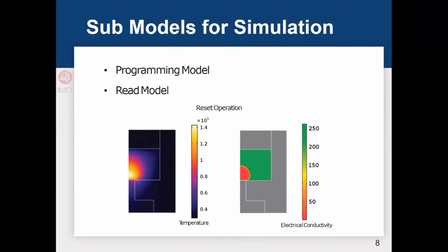So in the reset operation, we will have to increase the temperature so much that it actually crosses the melting temperature of GST, so it goes into the amorphous state, and the resistance is actually so high. And in this picture, we can see there is a white, small line that's showing the temperature over the melting temperature, 873 Kelvin. This is the region actually going into the amorphous state, and above the other states are still in the crystalline state. And on the right side, we can see the electric conductivity. The lower side of the GST region is actually showing a lower amount of electrical conductivity compared to the upper side.